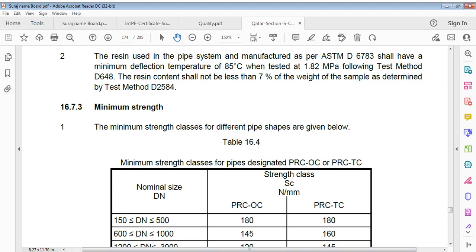Resin used in pipe system and manufactured shall have a minimum deflection temperature of 85 degrees Celsius when tested at 1.82 MPa, following test method D648. Resin content shall not be less than 7% of weight of sample as determined by D2584 test method. Minimum strength classes for different types, different pipe shapes are given below.